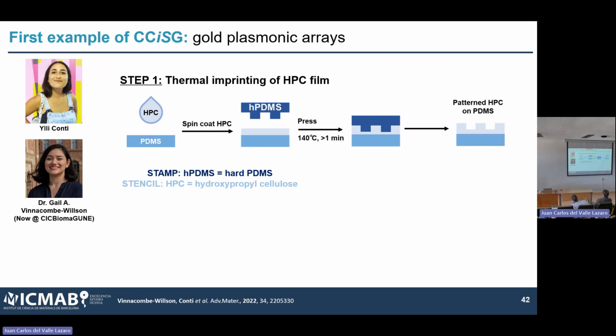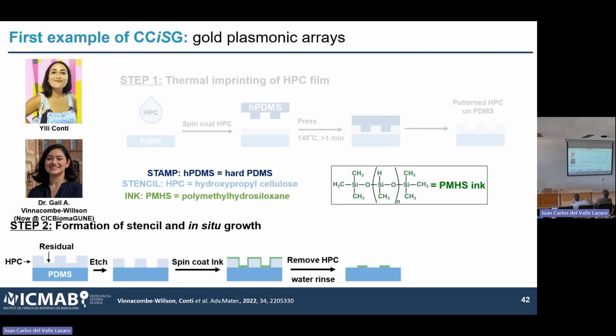to come up with. And the idea is we use hydroxypropyl cellulose, which is a polymer that is thermodeformable and that it can be washed out with water. We spin coat it, and then we use a stamp to make holes in it. Okay, so then we etch the residual layer so that we got basically a fishnet with holes. So we expose the PDMS underneath, and then we apply this ink. And the reason we chose this ink is that there is this chemical bond, which is a reducing chemical bond, and we know that this can nucleate particles.